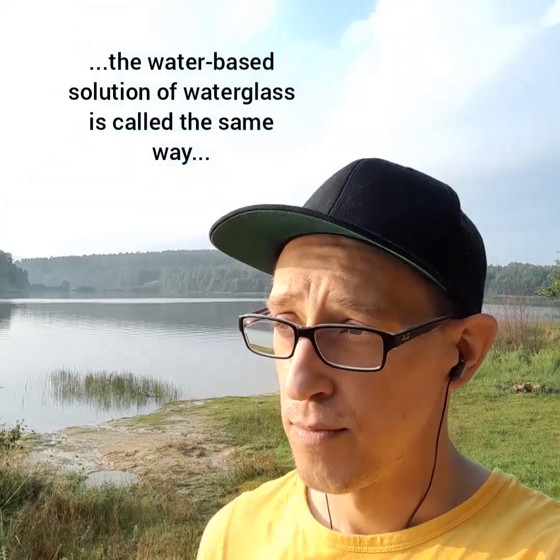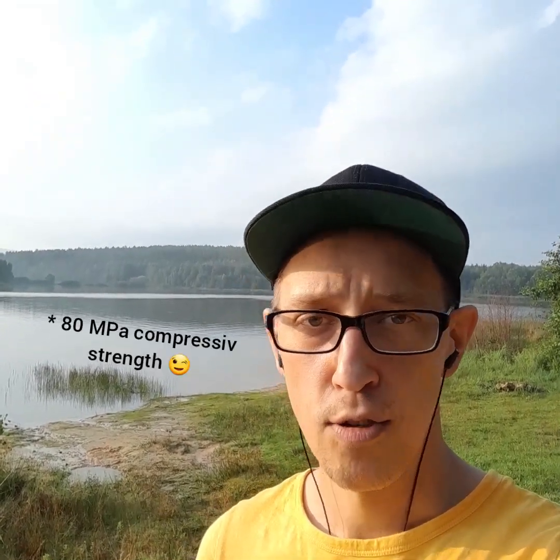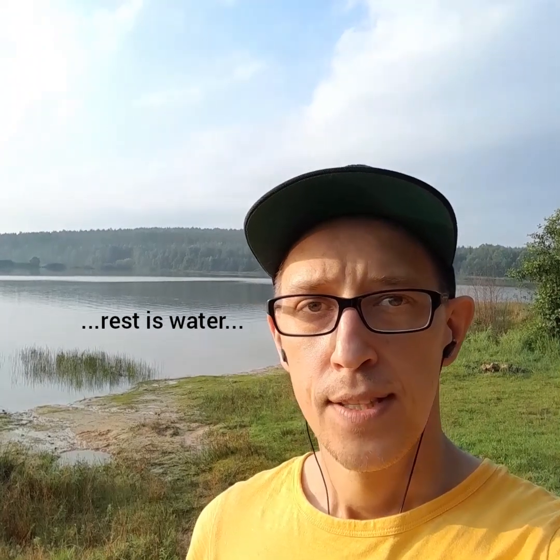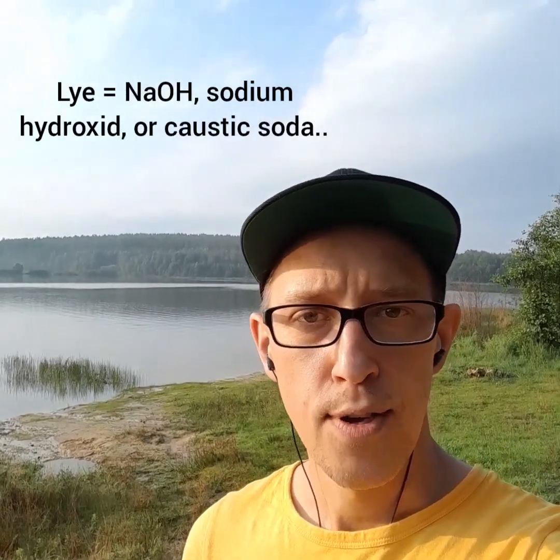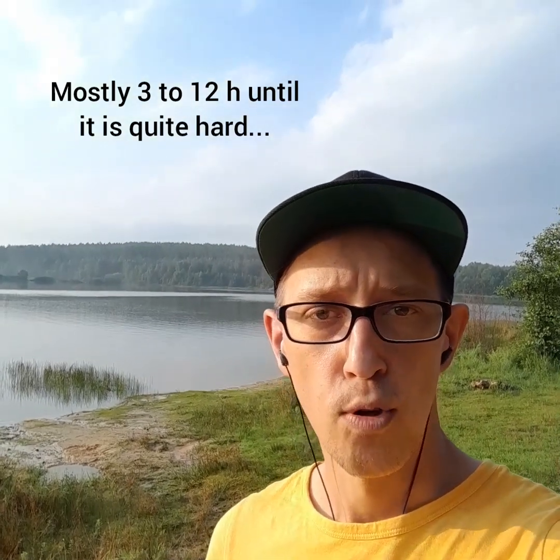Quite recently, I made a geopolymer with 80 MPa compressive strength and a fantastic freeze-thaw resistance, and it contained only 7% of metakaolin, this clay mineral, and 3% of solid water glass. So we take burnt clay, some water glass, and some lye, the same lye you need for pretzels. Then you mix it and you have a slurry. Most of the time you mix in some stones and gravel, because that is relatively cheap. The geopolymer is relatively expensive, so it's one part geopolymer and 3 to 4 parts of the so-called aggregates, and then normally 24 hours later it has hardened into a geopolymer concrete.